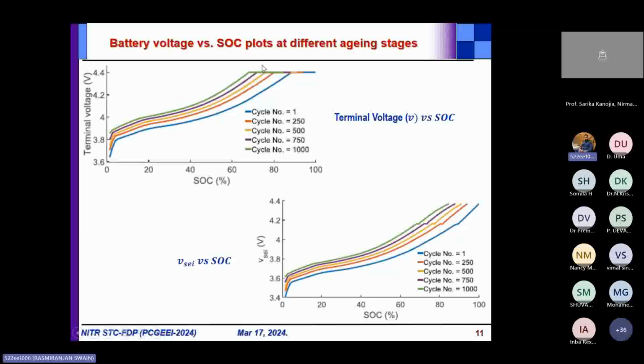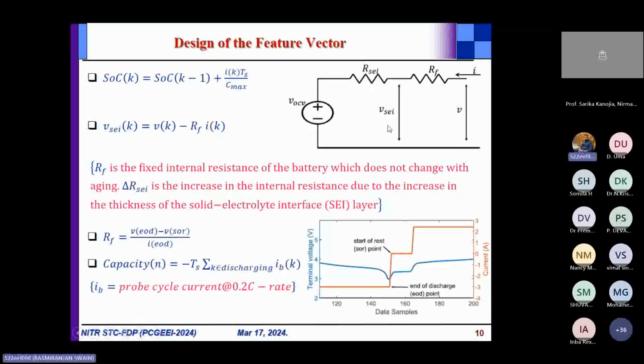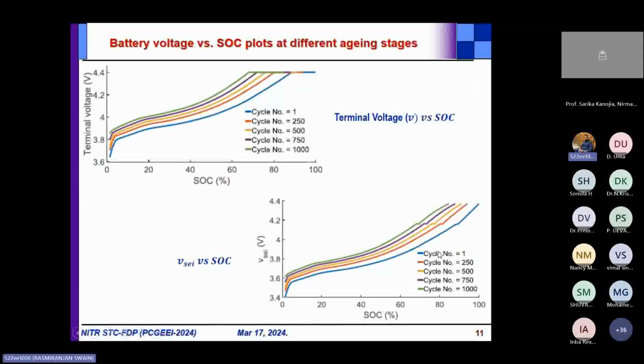Gradually you can observe that the terminal voltage reaches the max value at a lower state of charge as the battery has aged, because at this point the battery is the most aged one, that is at 1000 cycles. Here the state of health is the lowest, and here the state of health is the maximum. Similar thing you will also notice if you see the variation of the v_sei voltage versus the state of charge. A similar trend has been observed here also. That was the first plot, the terminal voltage, and this corresponds to the second plot shown here. You can notice a similar shift in the x direction due to the aging factor.